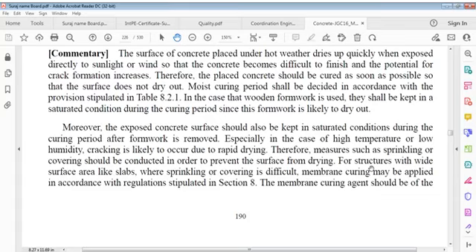Surface of concrete placed under hot weather dries up quickly when exposed directly to sun or wind, so that concrete becomes difficult to finish and potential for crack formation increases. Therefore, placed concrete should be cured as soon as possible so that surface does not dry out. Moist curing period shall be decided in accordance with table.